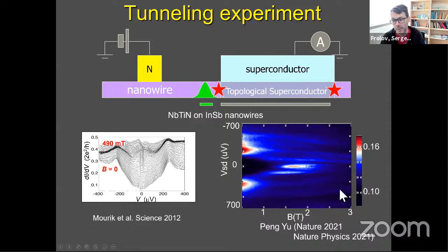Now, this color scale representation is the one I'm going to use more often, and has the same features in it, like bright red bumps here at low field, those are the edges of the induced superconducting gap. And inside the gap, black is a suppressed conductance. So it's not zero, but it is suppressed. And then this streak, like I mentioned, is a zero bias peak that appears at finite field. And then there's all these other states that we can explore, but we still don't know precisely what they are.